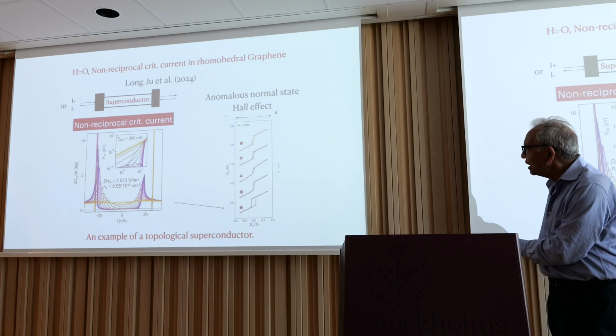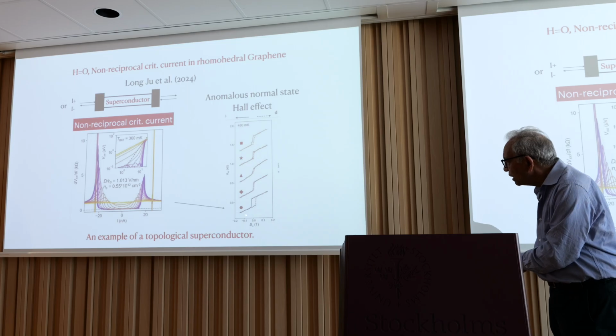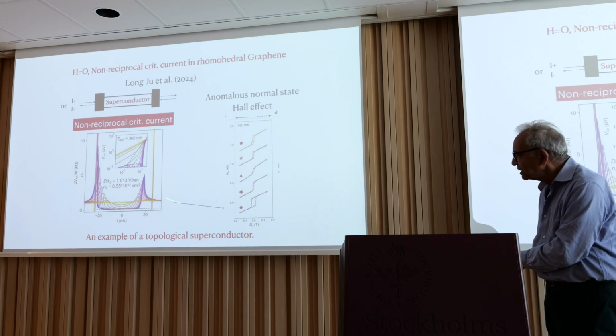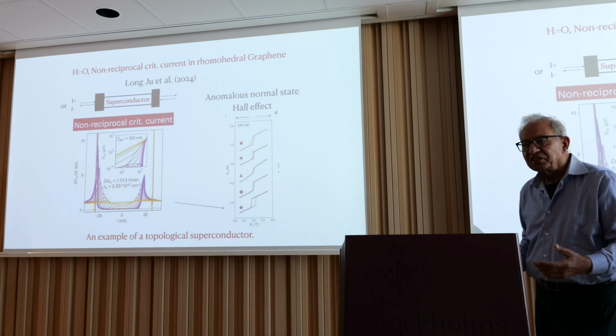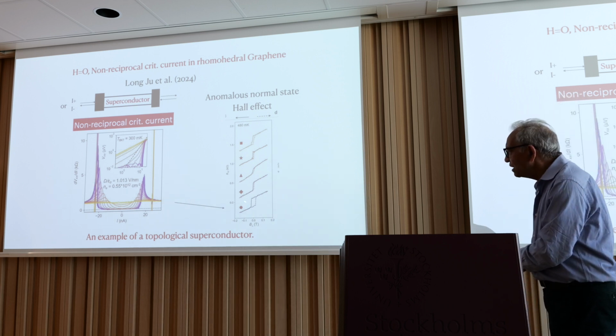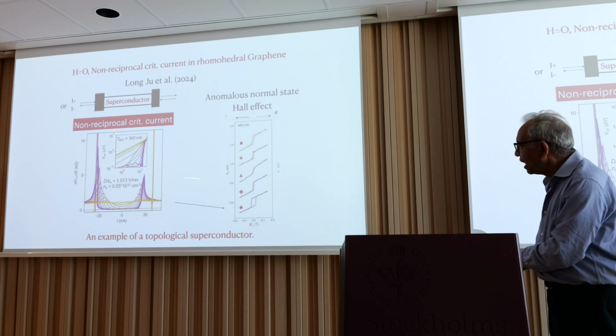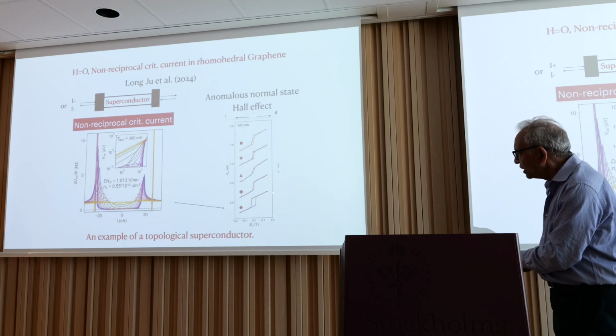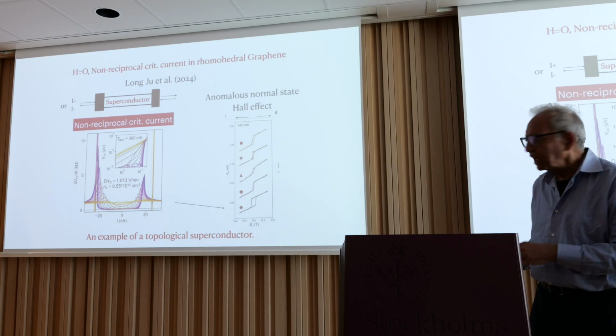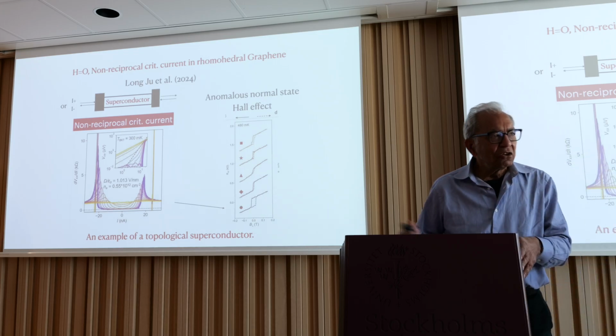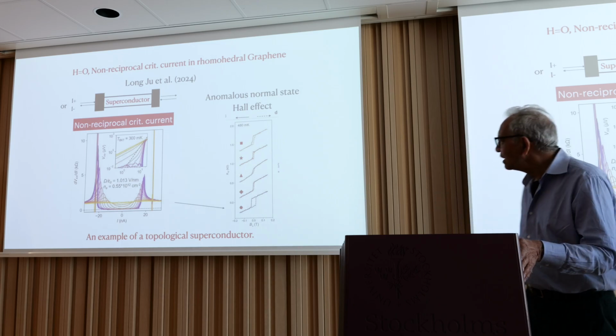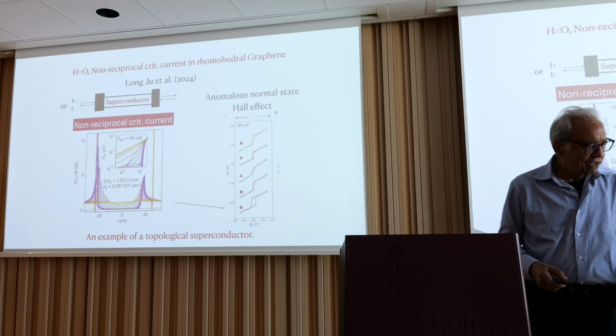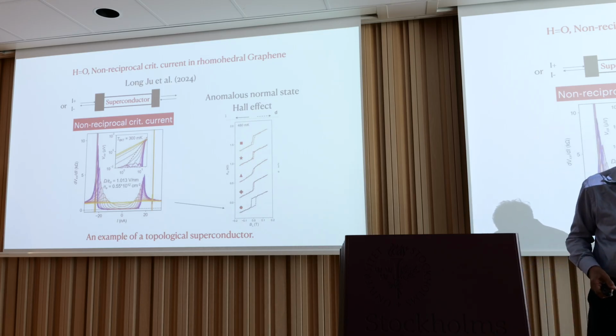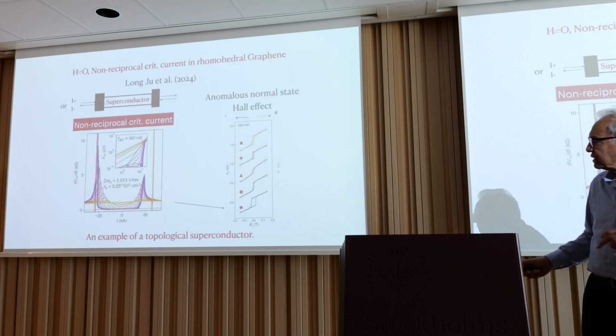When he goes to the normal state at 480 millikelvin, he can measure Rxy, the Hall resistance, and he discovers that the Hall resistance is unquantized. However, it is spontaneous in the sense that by the time you apply 100 Gauss, the Rxy sign switches from one to the other. So this is the hysteresis characteristic of going from one to the other, and this is rather simple and beautiful. And so this is clearly a case of a topological superconductor with anomalous Hall effect in the normal state.